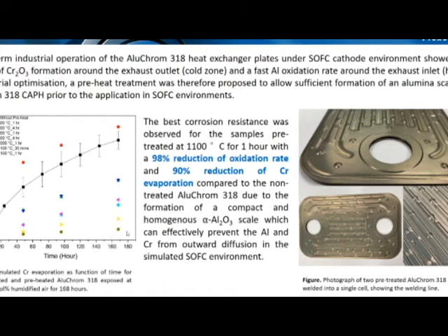So finally, we found the sample pre-treated at 1100 degrees for 1 hour has the best performance with 98% reduction of oxidation rate and 90% reduction of chromium evaporation. So the photograph on the right side shows a single cell of AluChrom 318 heat exchanger after pre-treatment at 1100 degrees for 1 hour. The color is different from the original plate because it is covered with alumina on the surface formed during pre-treatment. So next step, we will put this pre-treated heat exchanger in a real test.